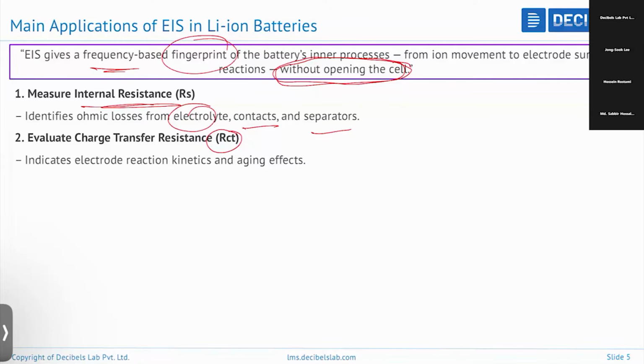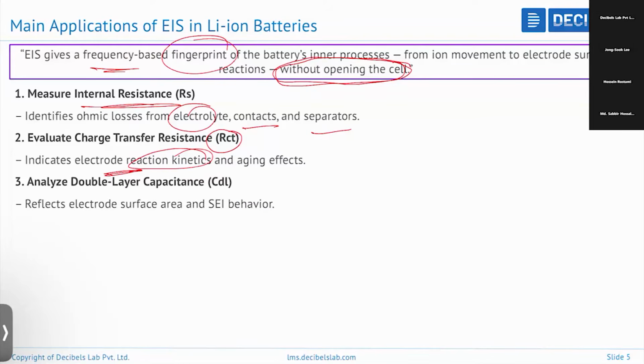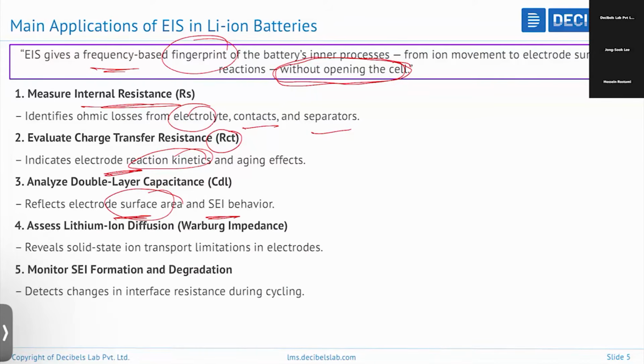So it indicates how the electrode reaction kinetics and the aging effects are. And then we can also analyze the double layer capacitance. This corresponds to the formation of the double layer, the accumulation of charges. It reflects the electrode surface area and also the solid electrolyte interface behavior. And EIS can also assess lithium-ion diffusion. This is represented by Warburg impedance. It reveals the solid-state ion transport limitations in electrodes.